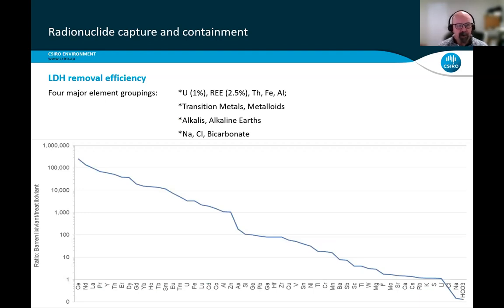Okay, if we have a look at now layered double hydroxide removal efficiency for a whole range of elements. So we've got, I should point out first on the y-axis, this is the ratio of the barren lixiviant, so the untreated lixiviant to the treated lixiviant, so the contaminated to the decontaminated. And we've got a whole range of ratios there, everything from pretty much a ratio of 1 through to a ratio up to almost a 1 million times in terms of the ratio of dirty to clean, effectively.